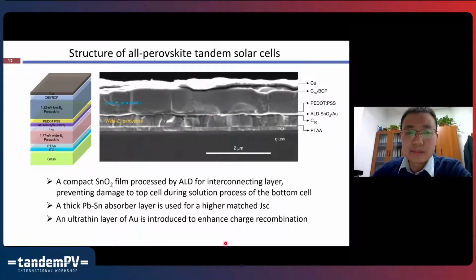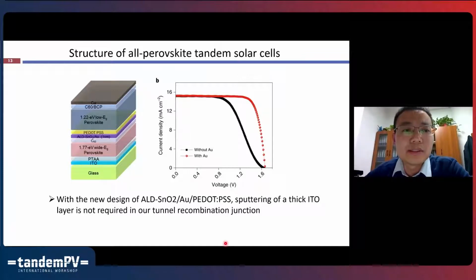But still, we have another issue, because the atomic layer deposited tin oxide layer has a very poor conductivity, so it's not good enough to act as the tunnel recombination junction. So to accelerate the charge recombination in the tunnel junction, we also add a very thin gold nanocluster layer, like a 1 nanometer gold layer by thermal evaporation on top of the tin oxide layer. And with these gold nanoclusters in the tunnel junction, we can much improve the fill factor of the tandem devices.